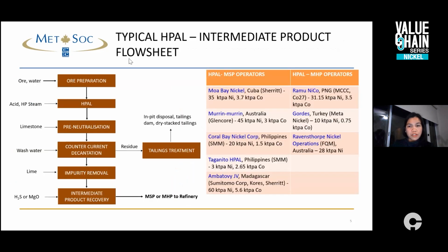So this is a typical flow sheet of an HPAL process. So first, the ore is prepared, basically rejecting the majority of the barren ore. What we're rejecting here is magnesium, which I said earlier consumes a lot of acid, and then we prepare the ore into a slurry form and feed it into high pressure acid leaching, where we add acid and high pressure steam to keep the pressure and leach the ore. Then the nickel and cobalt is leached into the solution. But in HPAL, one of the control parameters there is free acid, in order to keep your nickel and cobalt in solution.